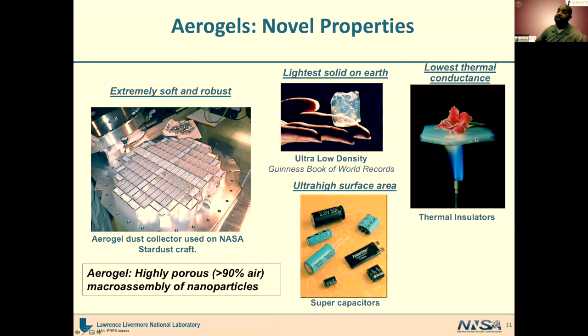They have very, very good insulating properties. This is because transport in general is not good through aerogels. They're very tortuous because they are made up of nanopores, and so transporting anything, heat, any sort of mass transport, through an aerogel is challenging. Here you can have a several 100-degree flame on one side of this approximately centimeter thick aerogel, and you're not even singeing the petals of a flower on the other side.